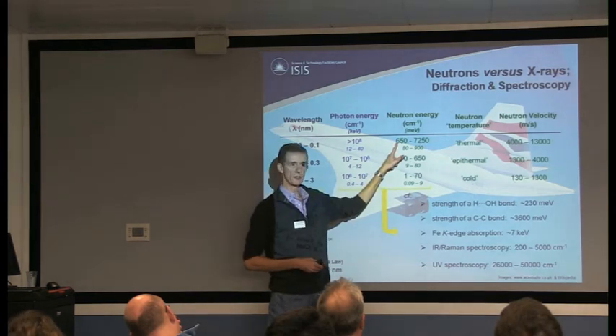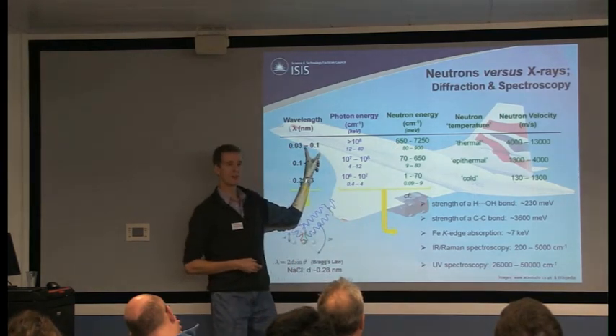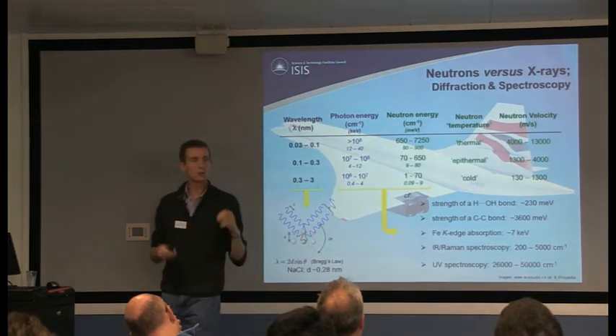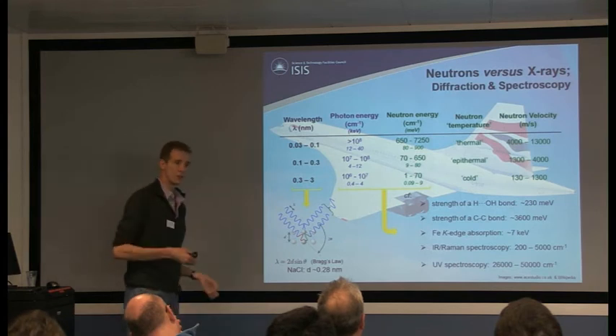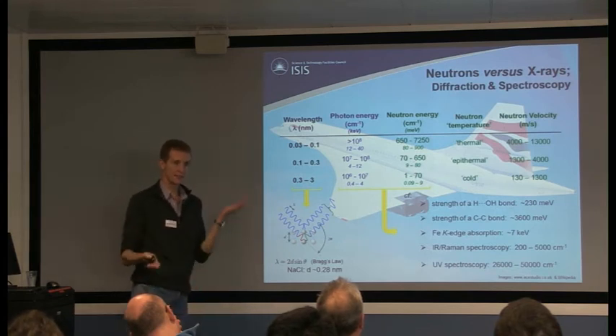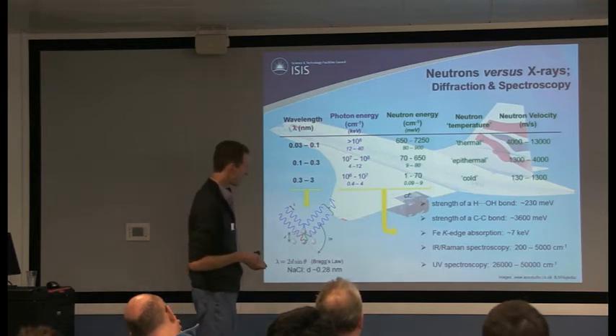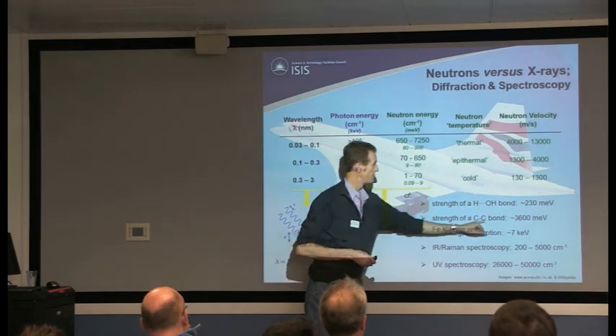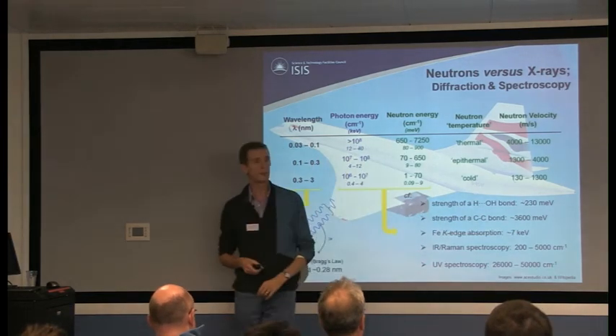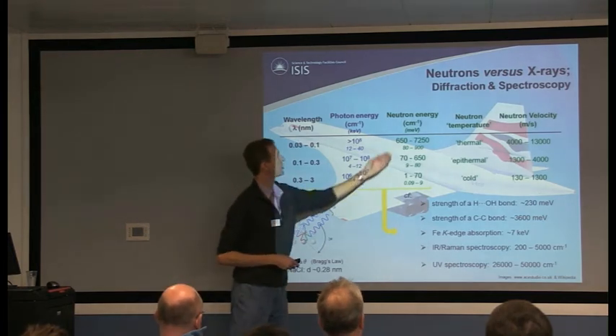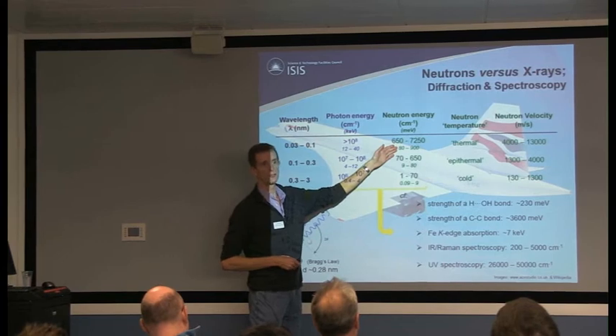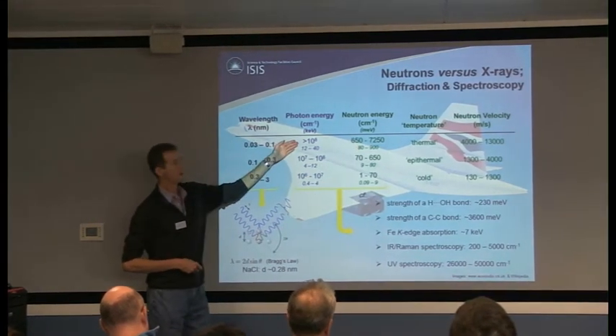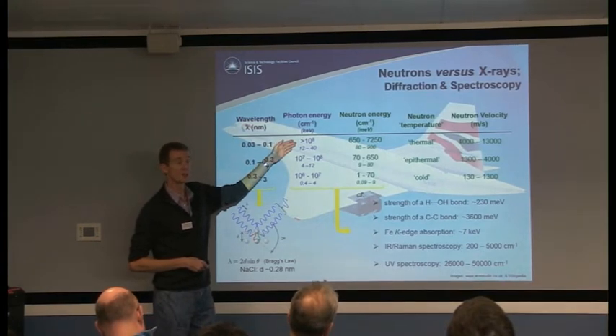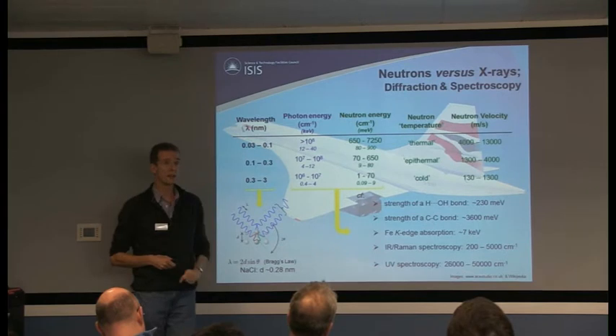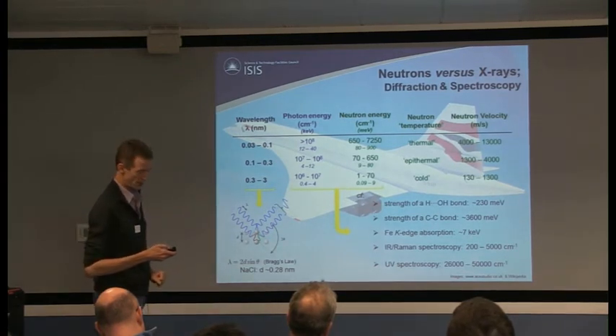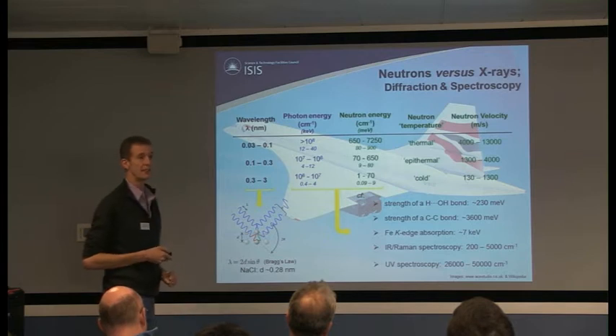However, you can do molecular spectroscopy with neutrons, providing you use neutrons of about the right wavelength. We can't do the chemical spectroscopy that you can do with X-rays, so there's an example of the complementarity. Typical bond strengths are usually a few thousand milli-electron volts, which are comparable to the energies of our neutrons. But those bond strengths are much, much lower than the energies of X-ray photons, which is why X-rays are very damaging, particularly to things like biological material.